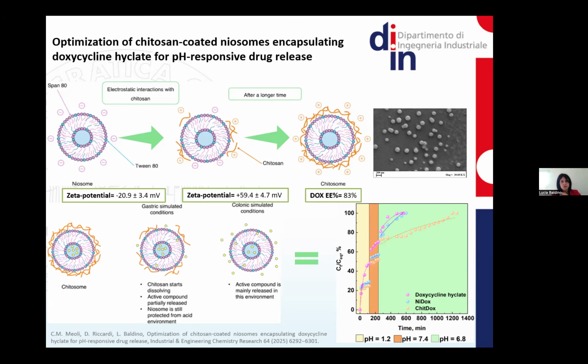We also encapsulated in it doxycycline hyclate, that is an antibiotic, reaching an encapsulation efficiency up to 83%. And then we tested the performance of chitosomes in order to validate the pH responsive drug release. So we prepared 3 different liquid media at different pH in order to simulate gastric, small intestine, and colonic conditions. That was our goal, and we verified that most of the doxycycline release was obtained in the last region, at pH 6.8. That was our purpose.